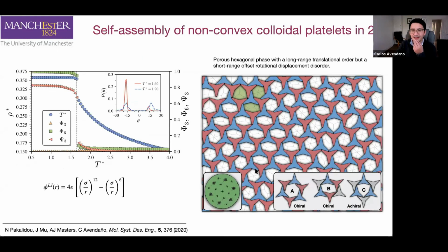We observe that the system tends to form some type of hexagonal structures with very high porosity. You can see that there are big holes here because the particles cannot pack very efficiently. But the way that two particles, or several particles, will interact will form these pores or these holes in different symmetry, either forming chiral symmetry or non-chiral symmetry.